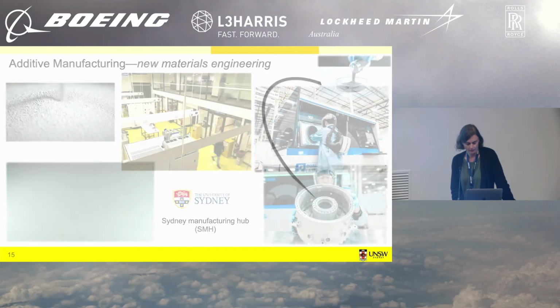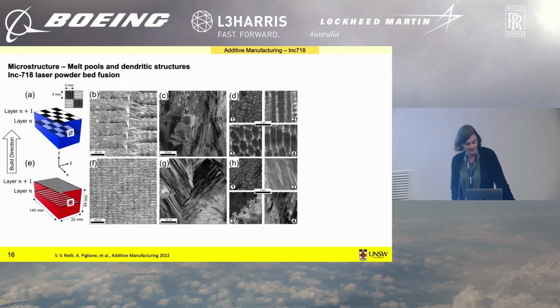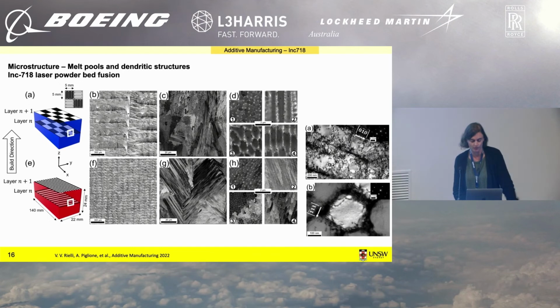So just coming briefly back to the Inconel 718 example, that's what we've seen before, the turbine disc. I'm not going to go into too much detail, but rather than playing with the forging, in 3D additive manufacturing we can play with the scanning strategy of the laser beam in this case. So you can see here a chessboard pattern, and at the bottom you can see a linear pattern, and again you can create vastly hierarchical and different microstructures. I'm not going to go into any detail here, but we again need to study them across several length scales to understand how we can achieve better properties.